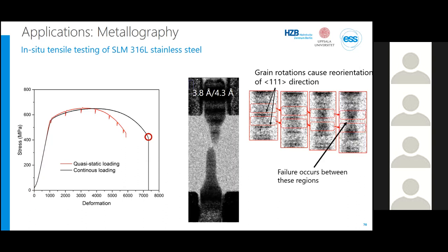And then this ultimate failure, when the sample actually breaks, we are actually able to track this back, that this is happening in between these overlap regions. So this laser scan strategy creates this overlap region basically, and that somehow is the weakest spot where the sample will actually break later on. And this we would have not seen otherwise.